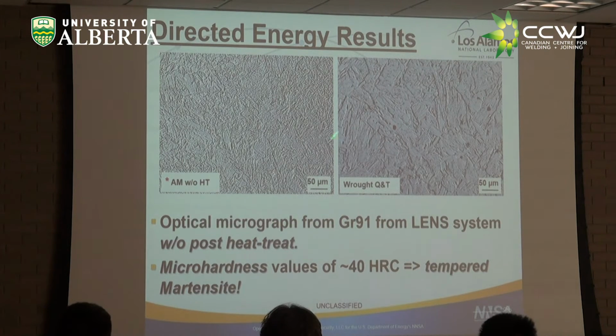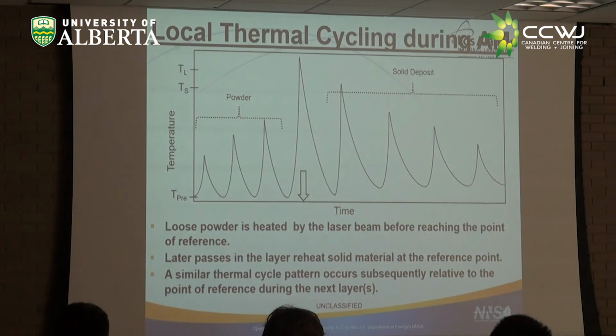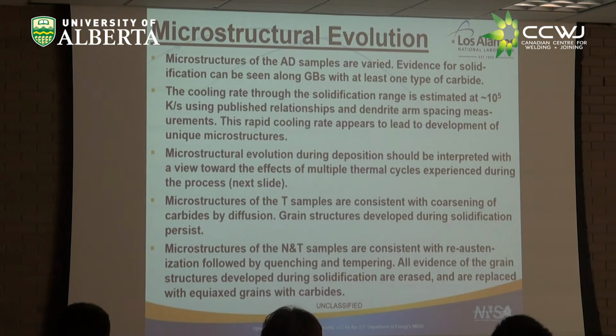And what do you see there? This needle-like microstructure is characteristic of martensite. So it is possible with other additive processes to get the microstructure you think you should have. I probably should have put that first. But it appears that this really rapid cooling matters. The cooling rate in the micrographs I just showed you is probably on the order of 10 to the 3, maybe up to 10 to the 4, but it's hard to tell because I don't have dendrite arm spacing to measure and estimate from. But it's a much slower cooling rate. So something about this rapid cooling rate seems to produce these interesting microstructures.